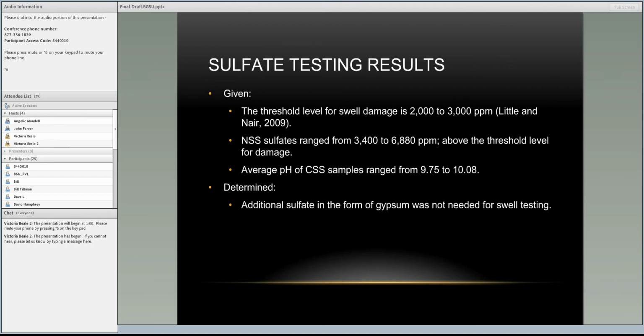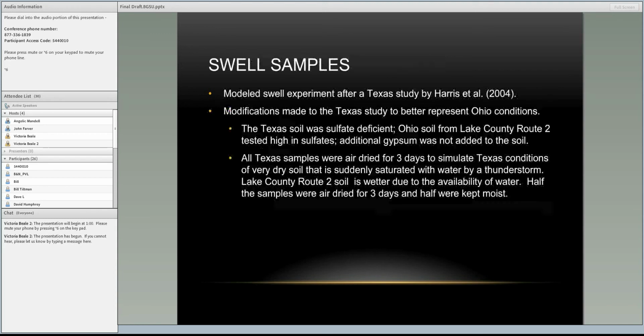In modeling the swell samples, we looked at a Texas study by Harris et al. 2004, and we followed that study pretty closely. We only made a couple of changes, and we made these changes to better represent Ohio conditions along Lake Route 2. The one thing was, after sulfate testing, we determined that we didn't want to add additional gypsum because that wouldn't really be representing the conditions at Lake County.